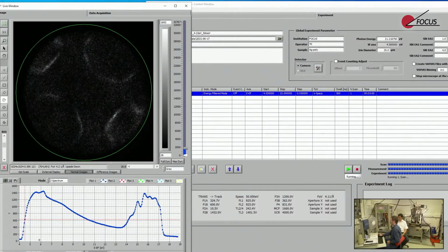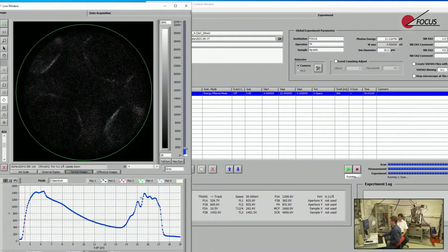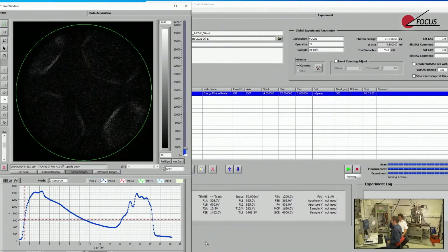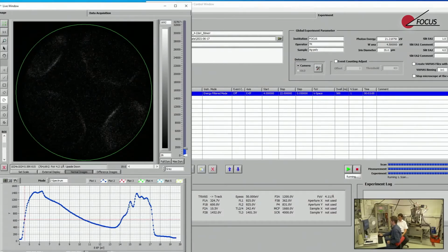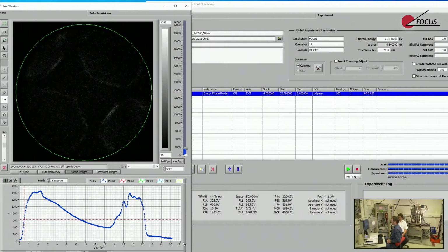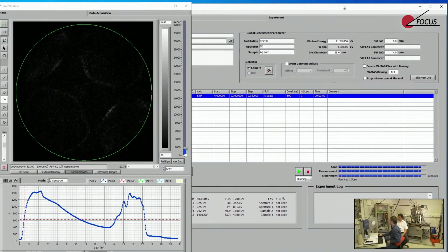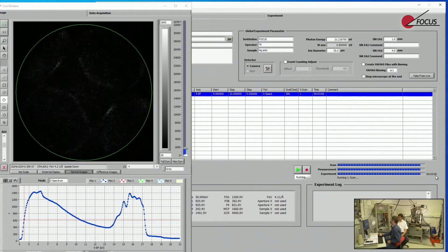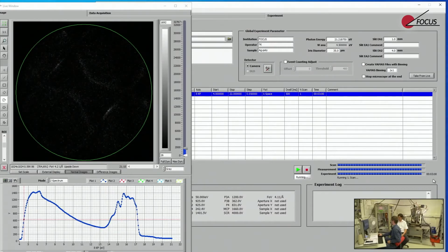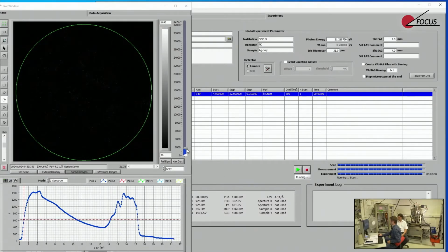Okay, so here you see the full spectrum of this silver crystallite. You see the D bands here, fine structure and the SP bands very low. And finally, the Fermi edge at 21.2 electron volts. And then we are actually finished. So the time for these experiments has been 3 minutes. Yeah, so now it's done.